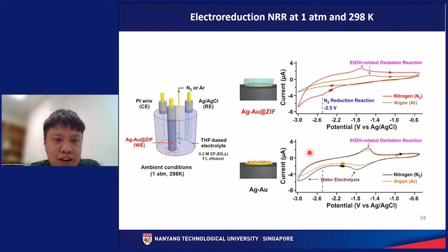After which we begin to characterize the reaction involved in our electrochemical system. In this case, we use an electrochemical system whereby it involves our MOF encapsulated platform as our working electrode, platinum wire as the counter electrode, and silver chloride as our reference electrode. Nitrogen or argon are continuously pumped into our system to drive our reaction or to provide an inert atmosphere. The electrolyte that we use is a dry THF based electrolyte, and it contains a lithium salt to conduct electricity. 1% ethanol is added, which serves as a proton source. The other key point is that all these electrochemical reactions occur at ambient conditions at 1 atm and 298 Kelvin.